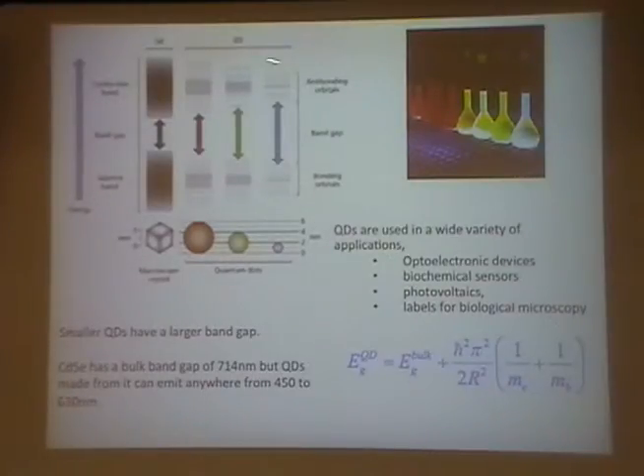Okay. I found this quite a nice diagram online to demonstrate what happens when we get different sized dots. So this would be the bulk case, so we have the bands, valence band and conduction band. But then when you go smaller, you get discrete energy levels, and the smaller the quantum dot, the greater the energy gap. So then you go between different colors, from red to green to blue. Okay. So then we can generate a whole range of different colors of quantum dot just based on the size. So the size effect is really important in these materials.